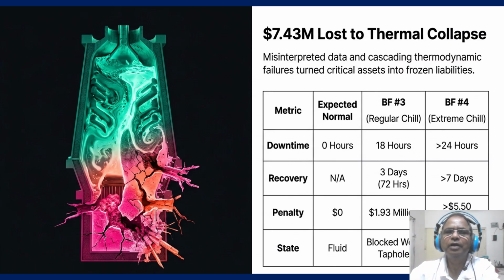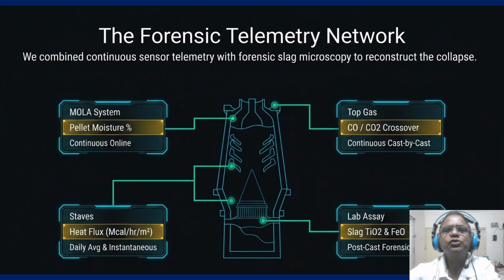Now, coming to our forensic telemetry network. To reconstruct this collapse, we combine four distinct streams of data. Follow the green line connecting the furnace schematic to the blue data box. At the top left, we have the MOLA system tracking pellet moisture percentage continuously online. At the bottom left, the staves are monitoring heat flux in megacalories per hour per square meter. Moving to the top right, we are looking at the top gas for that critical CO2 crossover. Finally, the lab assay at the bottom right provides post-cast forensics on slag, titania, and iron oxide.